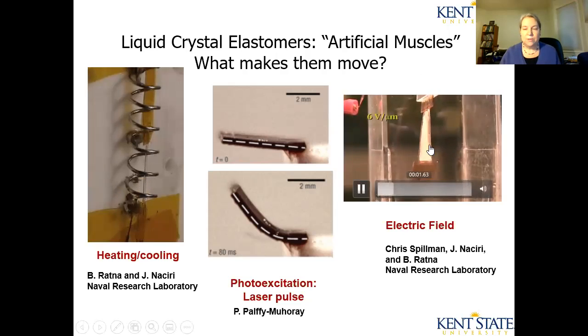This other video on the right side is also an experiment from the Naval Research Lab. This is a very thin piece of a polymer film that's been coated front and back by a conforming electrode. It is conducting grease, and then they're applying a voltage from the front to the back of the cell, just like you would do for a liquid crystal display. And what's interesting is it doesn't change color, it flexes. A positive voltage makes it flex one way, a negative voltage makes it flex the other way. So that's kind of interesting. It's a different effect than heating.